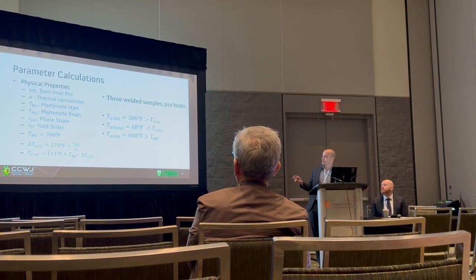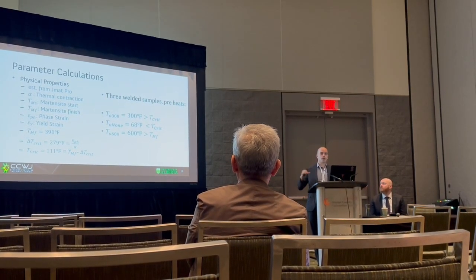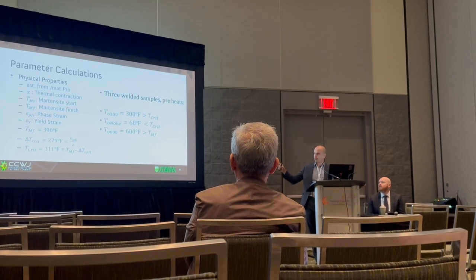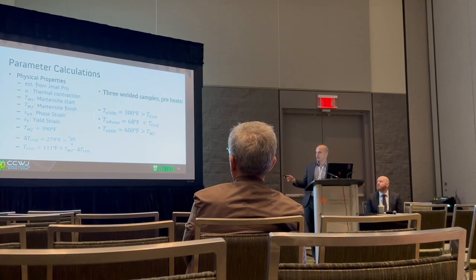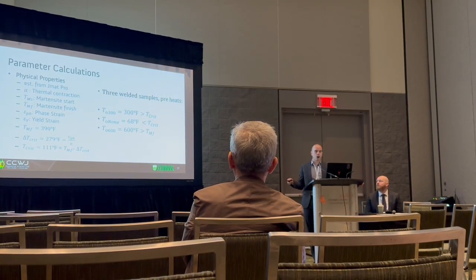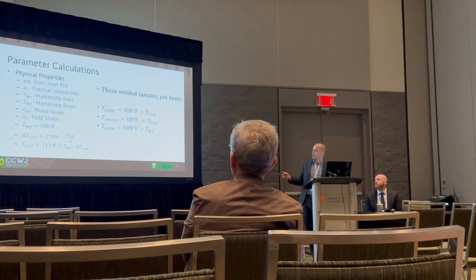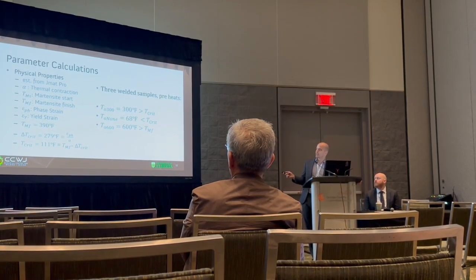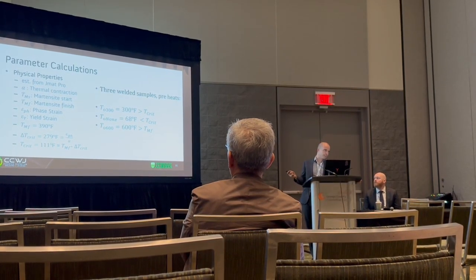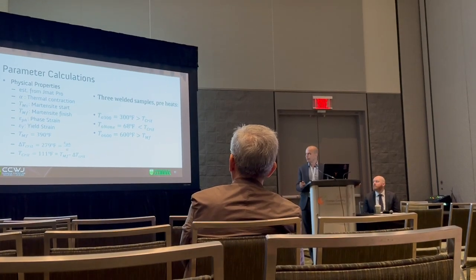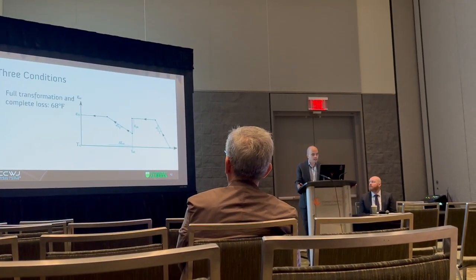We've got 300 degrees Fahrenheit. That's right in our sweet spot. We're above that critical temperature. Then we've got 68 degrees Fahrenheit, room temp. That obviously is well below, so it should be bad. And then we've got 600, and 600 is kind of unique. It's actually above that martensite finish temperature. So something weird is going to be happening there, but we'll look at it. So let's look at those three cases.